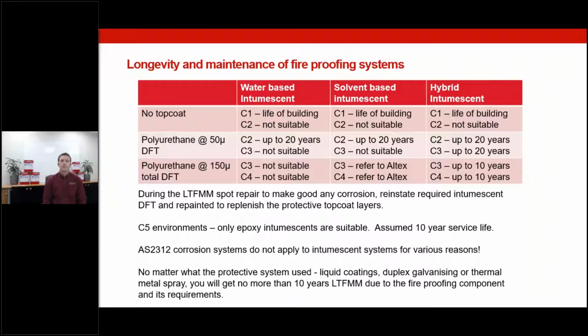No matter what protective coating system you're using, whether it be liquid coating systems, duplex galvanizing or thermal metal spray, it's that 10-year cycle that you're looking at for life to first major maintenance, due to the topping up of the polyurethane layer. Typically, that's what's used, and that's what needs to be replenished in order to bolster that first line of defense of the intumescent system that's been applied to your steelwork.